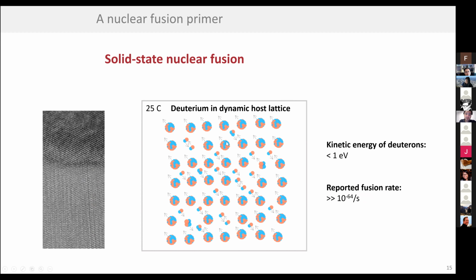This is what the solid state picture looks like. Here there's a depiction of some individual deuterium atoms. And again, deuterium is just an isotope of hydrogen. It's what people associate with heavy water. So if it combines with oxygen, you have heavy water, and you could even drink it. People describe it as kind of sweet. But it's what people like in fusion, because the extra neutron in there facilitates many kinds of fusion processes. So we like to work with deuterium instead of normal hydrogen. So anyway, here you have the deuterium sitting in between spaces in a lattice. Now this could be a titanium lattice or a palladium lattice, or any kind of lattice, and they sit in between there, just like carbon atoms sit in between an iron lattice in steel.